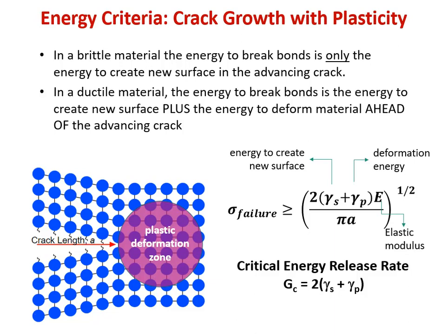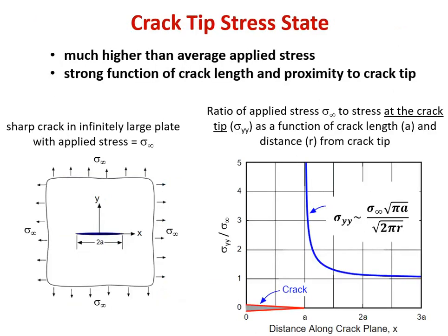We can write that again, simply the upper part that's related to our energy absorption mechanisms, as a critical energy release rate. And this is the energy release per unit advancement of the crack. In this case, the rate isn't a time dependence, it's a crack advancement dependence. So it would be a dx rather than a dt. So that G sub c, critical energy release rate, is 2 times the two energy absorption mechanisms, the surface creation and plastic deformation, of which the plastic deformation is a lot bigger.